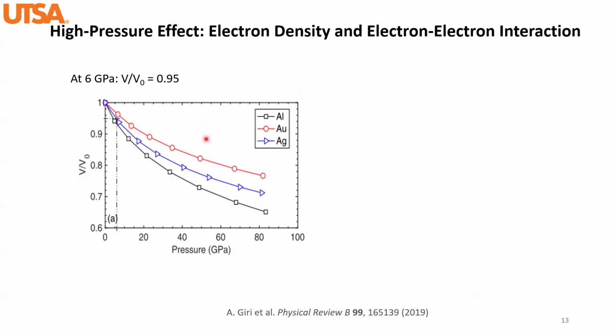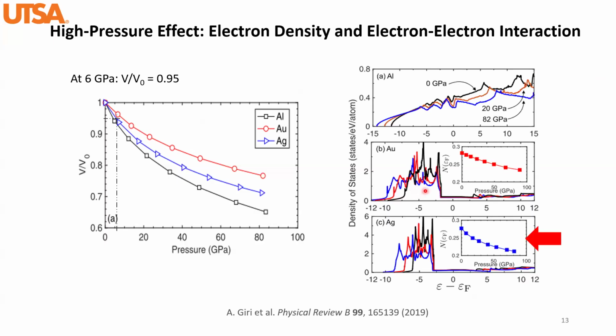The first thing we need to consider is the volume reduction, of course. Let's say the volume decrease of the cells of gold and silver. At 6 gigapascals, reading this figure, we estimate about a 5% drop in the size of the silver cell. Decreasing the total volume might cause an increased charge density, but it's probably not that simple, because the total number of electrons available at the Fermi energy level actually drops under high pressures. So I have to say that the electron-electron interaction might be really complicated in this case.